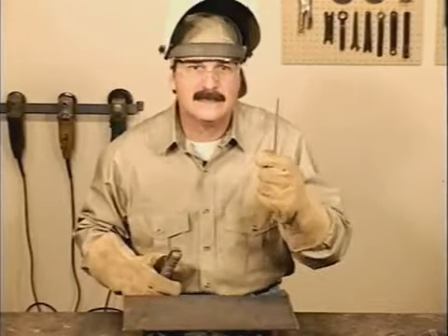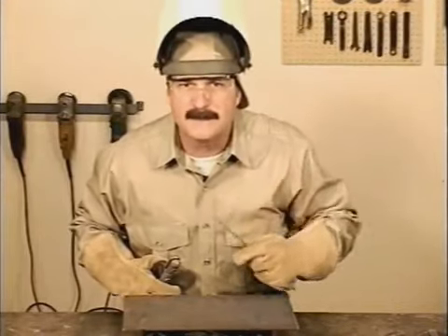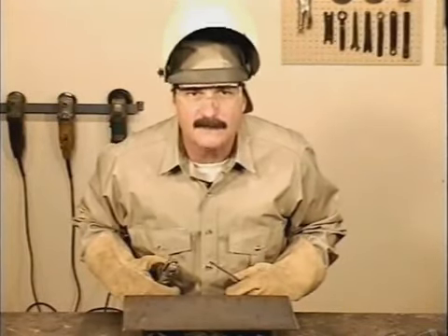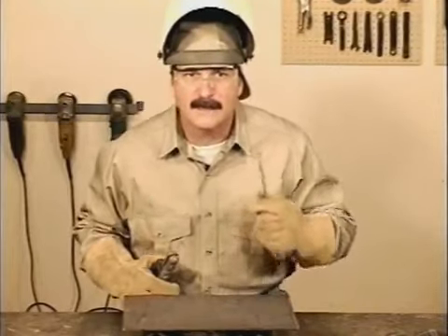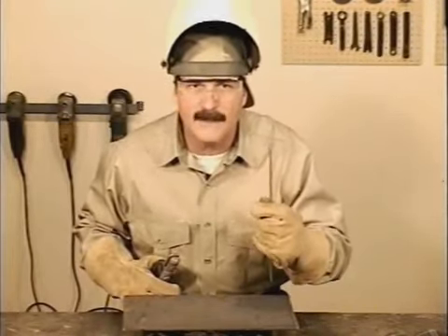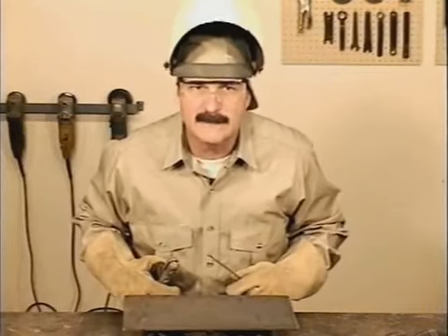This is a 1/8 E6010 electrode, and this is the most common size used. The manufacturer's recommended amperage setting is from 75 to 130 amps. They're saying this rod will work over a 55 amp range. The specific amperage setting is considered a variable and depends on metal thickness, position of the weld, and the welder's ability. The whole purpose in arc welding is to get the base metals hot enough to melt, forming a molten puddle. If the amperage is set too low, the base metal doesn't get hot enough, and the puddle looks like it's following the rod around.